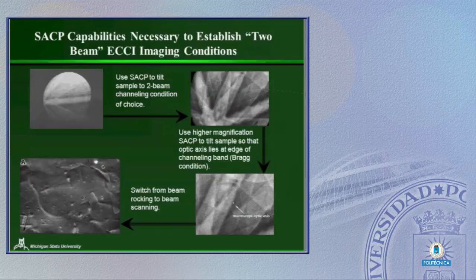How do we set this up? Well, in many ways, this is the same thing as you would do in a TEM. In TEM, what you would do is you would go to diffraction mode, you would tilt your sample to a 2-beam condition, you'd adjust your deviation parameter by moving your Kikuchi lines relative to the positions of your diffracted beams, and then you'd switch back to imaging mode.